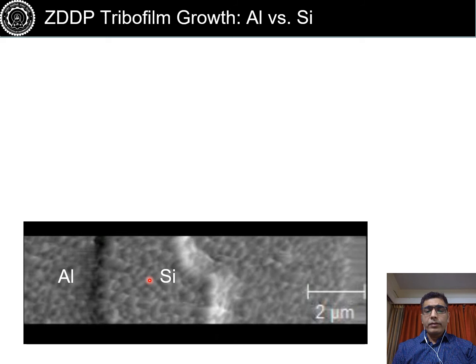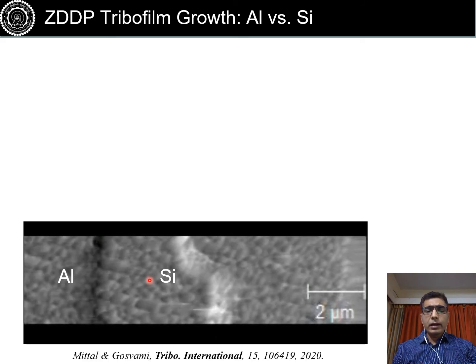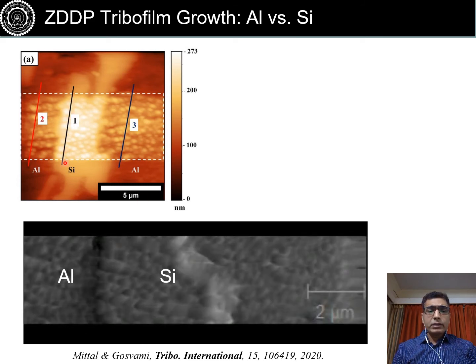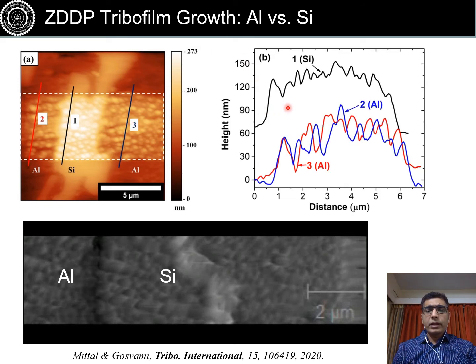Then we analyzed these tribofilms in more detail, and here is the final AFM image. So this is the silicon phase on which tribofilm has developed. You can see the islands of the tribofilm, and the aluminum matrix around it also has these films. But there was a clear difference when we look at the topography and height of these tribofilms. We saw that tribofilms were thicker on silicon, around 70 nanometers, with respect to aluminum where they were around 40 to 50 nanometers. And also the roughness of the tribofilm on silicon phase is very different compared to aluminum, where you see more gap between the islands of the tribofilm, so it's more patchy compared to silicon where there's more dense film.